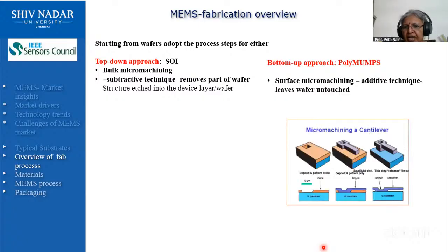So this is a standard example which I generally use initially for teaching. Of course, it's changed now. So the blue there is your substrate. You put in your sacrificial material, then deposit. I'm trying to make a cantilever, okay, through the bottom-up approach. So deposit your silicon on top and then you etch this portion off, you have a suspended cantilever. So this is a cross-sectional view of the same, right?